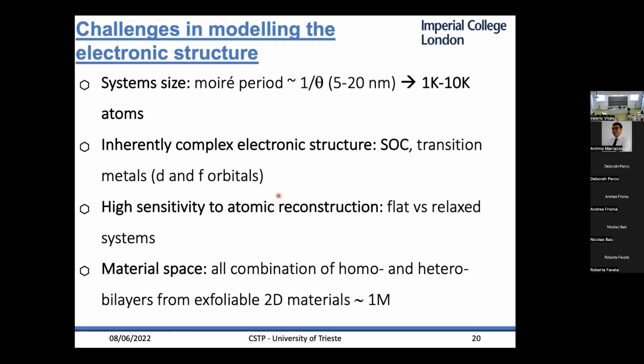For graphene, not really, graphene has quite a simple electronic structure, but for other materials like transition metal dichalcogenides, we have quite a complex electronic structure. You have transition metals where you have to deal with d and f orbitals, strong spin-orbit coupling, and so on. The other thing is that you really need to understand the relaxation of these systems, and this is quite important for the electronic structure, as we will see later. And you have this huge material space that comprises all the combinations that you can do with 2D materials, which is estimated to be around a million possible combinations.